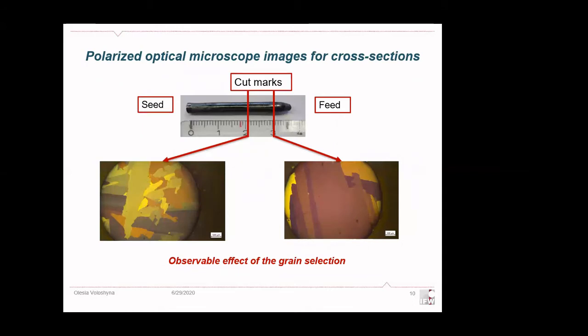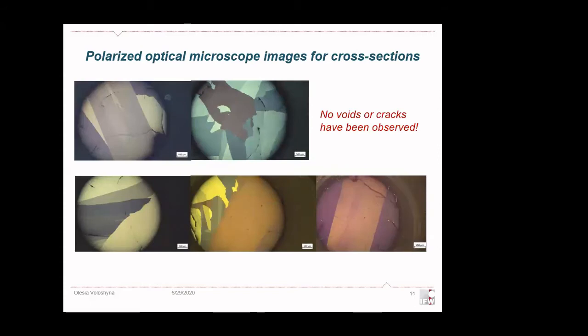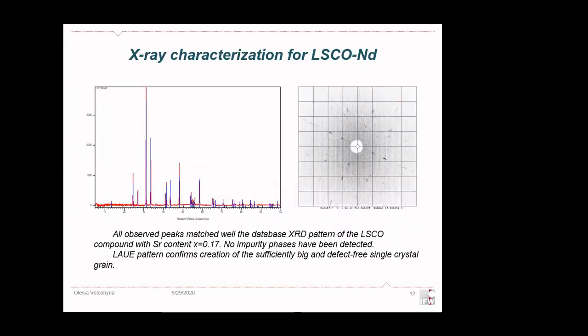And as you can see, the crystals present an observable effect of grain selection in them. And in the crystal, no voids or cracks were detected. The XRD results prove that in our samples we obtain the single phase of LSCO doped with neodymium, and the LAUE pattern confirms the creation of a sufficiently big and defect-free single crystal grain.